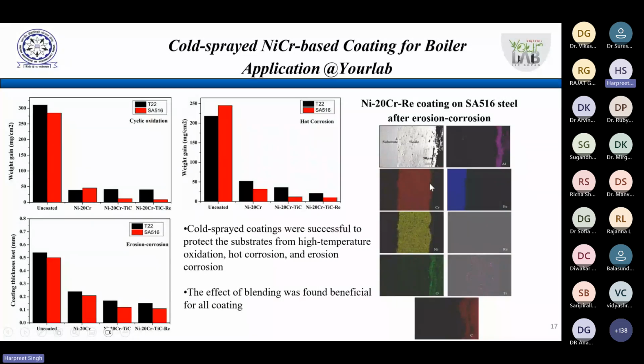So how did we do that? This erosion corrosion test was in fact done in the boiler itself. So we took these samples and we hung them into the boilers at locations where this erosion corrosion phenomenon is very severe. And then after exposure of 1500 hours, we took them. And you can see how intact these oxide layers are, or these coatings are still with the substrate.